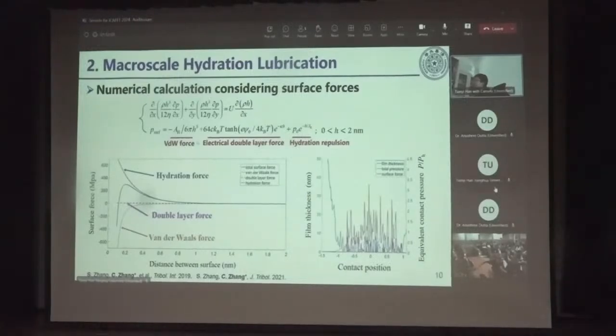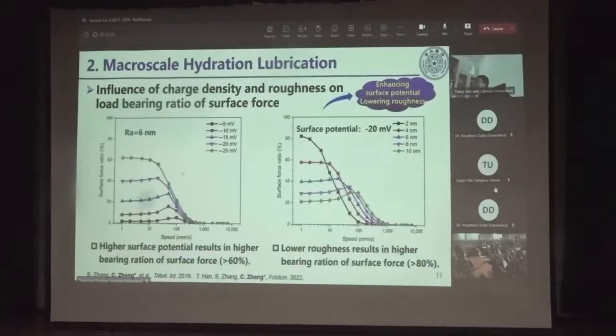effect. We introduced the surface force into the mixed lubrication model, and the surface force consists of van der Waals force, the electric double layer force, and the hydration repulsion. And I want to emphasize that the key is the hydration repulsion, because it is a very strong repulsion. And then from this we can calculate how many contact pressures can be supported by the hydration force. Let's see what happened. Let's see the results.